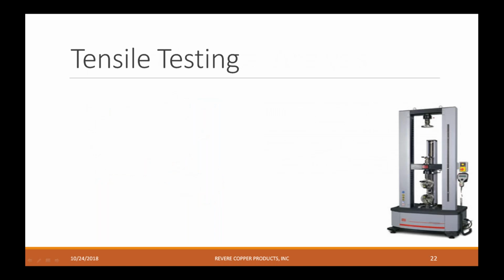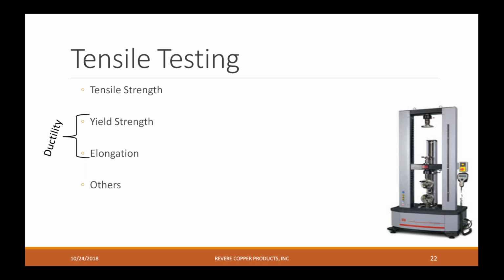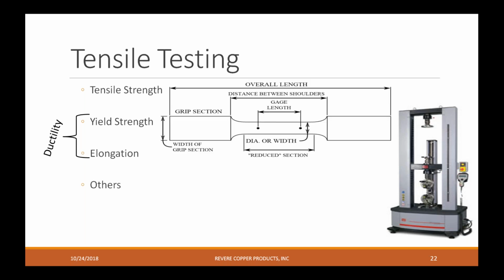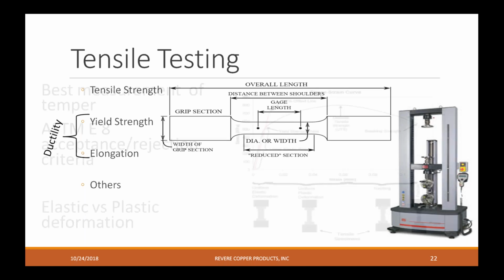Then we do tensile testing. So with tensile testing, we're testing for yield, elongation, tensile, and then there's actually others that can be determined through this test. Again, ductility is your yield and elongation. And how do we do that? We take a sample of that metal at its finished gauge and temper, and we cut it into this dog bone shape. And then that gets turned vertically and put in the machine that's pictured to the right, and we pull on it on both ends.